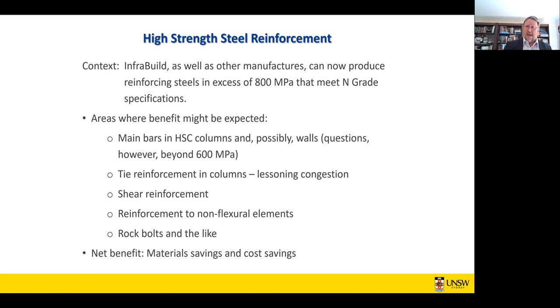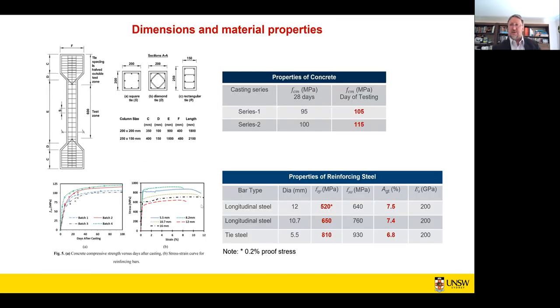And then the question is, well, where can it be best used? Where can the performance of these high strength materials be used? And columns is one area. The question is, well, have we maximized yet? We started that work only about 5 years ago, probably one of the shortest periods of time from when the work started to getting it into a standard. But the question is, have we actually maximized the benefit from that reinforcement? That's something I'll talk about in a minute. Tie reinforcement, shear reinforcement's an area I think we really need to look at as well, because essentially if we can increase from 500 megapascals to 750 megapascals, we can use a third less material.